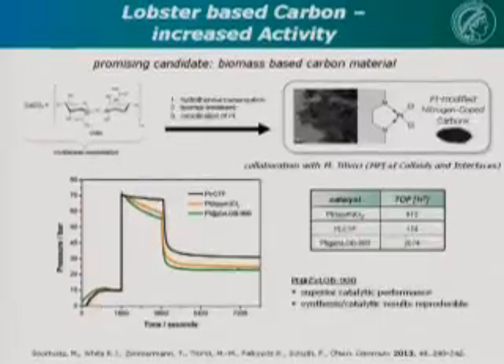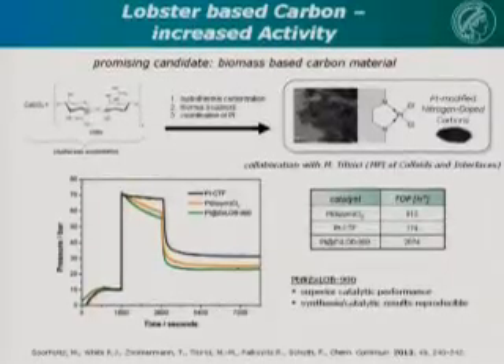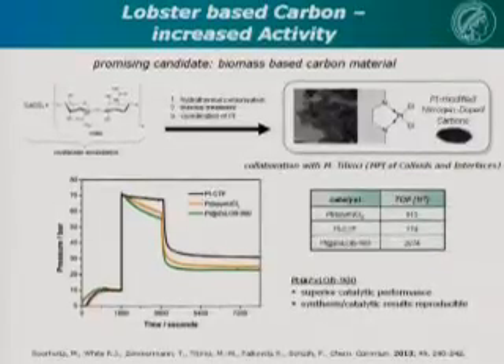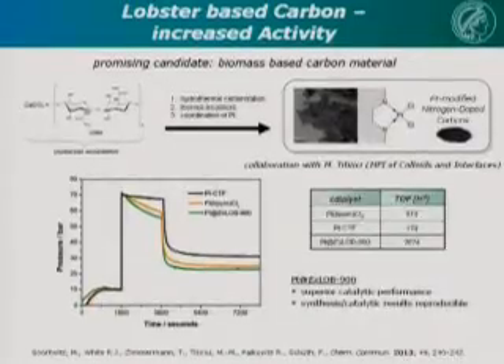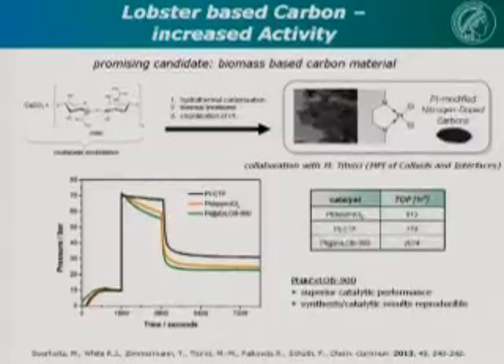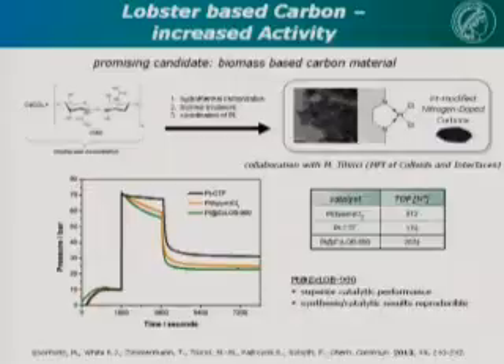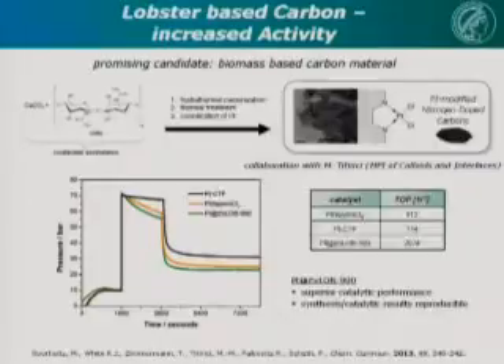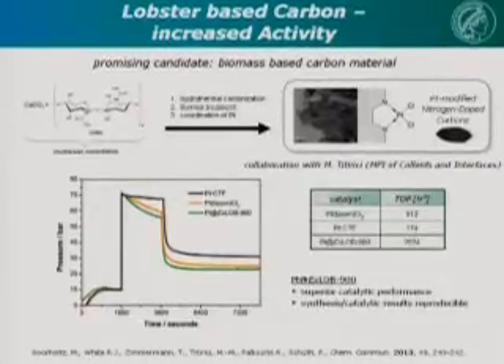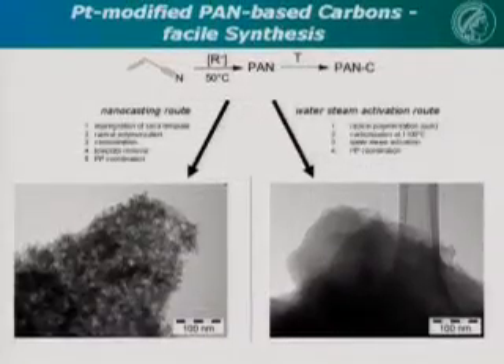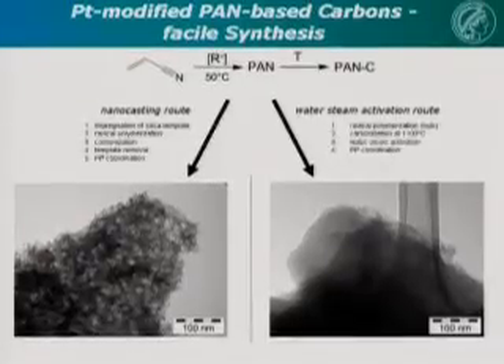The way we did it before was just we filled a batch, pressurized with methane, after an hour looked at the products. We have now built a reactor where we pressurize with methane, can then follow the pressure drop, and from the initial slope, get kinetics, real rate data on this process with true turnover frequencies per platinum site. And as you see here, the lobster has twice the activity as the Periana system.